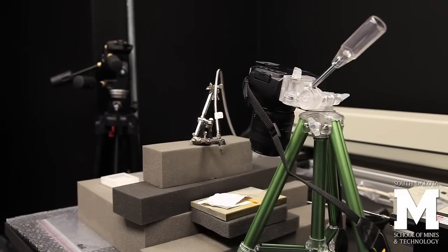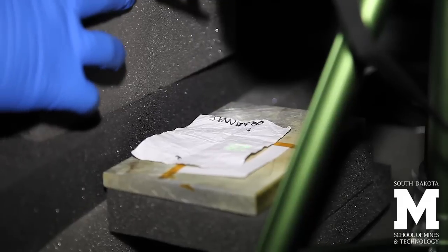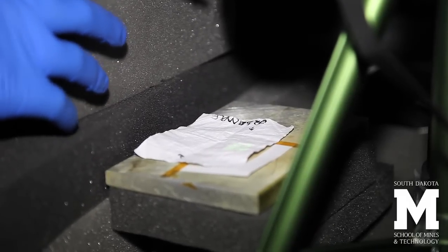This is the 980 nanometer laser we got, and it's got 8 watts power. Once we excite these QR codes using this 980 nanometer laser, they show up in green color because of that upconversion.